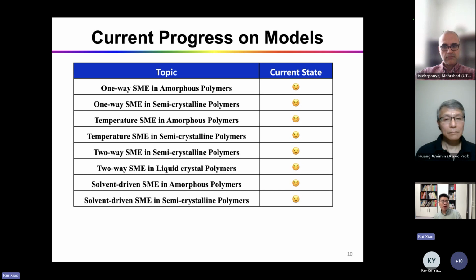It's no problem. For the solvent-driven shape memory effect, we can model that in amorphous systems, but we cannot model that in semi-crystalline polymers. So you can see for amorphous systems, the model is not a big problem, but for semi-crystalline polymers, the model is still a big issue.